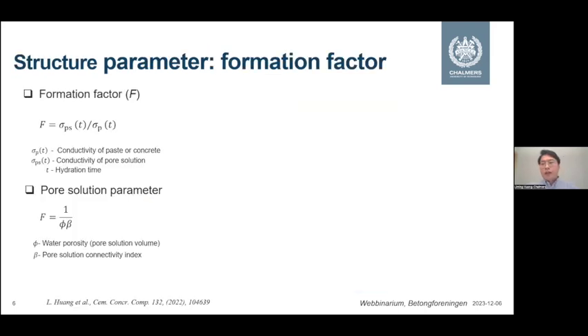What we can extract from the electrical conductivity or resistivity data are some parameters that try to quantify the correlation between the electrical properties of cement-based materials and the pore structure, like the pore connectivity parameter, which, as Claudia has mentioned, is important for durability modeling or prediction. We have the formation factor, which is defined as the electrical conductivity of the pore solution divided by the electrical conductivity of the paste or concrete, which we can measure or monitor with this device. The second equation shows the correlation between the formation factor and the volume of pore solution and its connectivity.